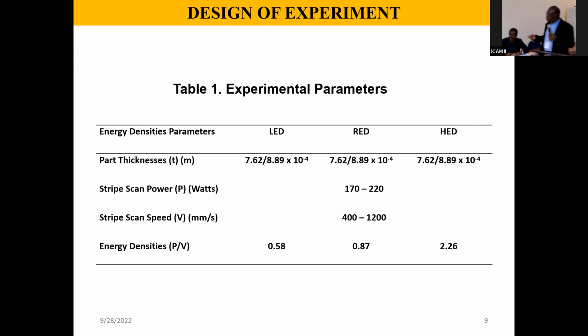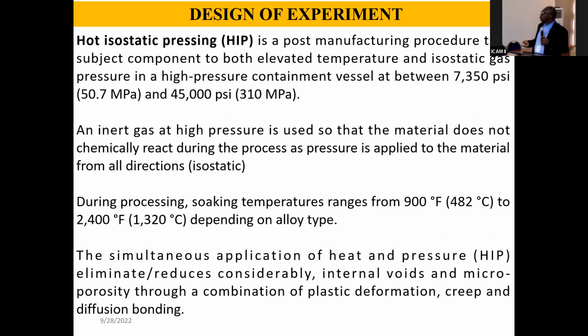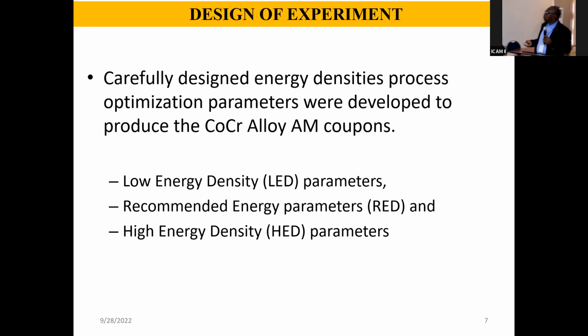So we have carefully designed energy density processes that essentially have low energy density. We have the recommended energy parameters from the industry. Oftentimes when you buy this powder, the original manufacturer will give you parameters that they consider optimal to produce them. So what we did was to vary this parameter from the recommended energy density parameters, going to the high and the low density parameters.